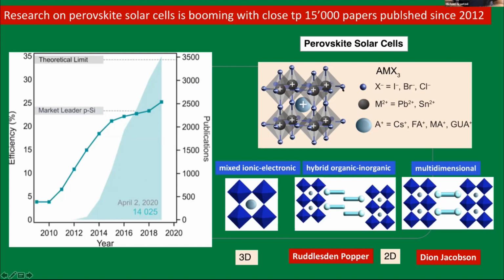So these are highly complex systems. You can change the anion, you can change the so-called B cation, lead, tin, or germanium being used, but there are other B cations. They just are not as colorful as the ones we are using for photovoltaics. And so the A cation is the charge compensating sitting in this cavity. And so the cavity is just the right size for cesium, formamidinium, methylammonium, and also guanidinium. But then, as I said, the conductivity is mixed ionic electronic.